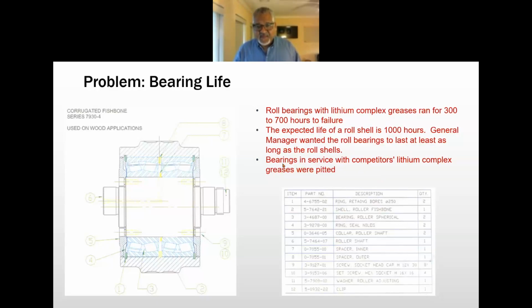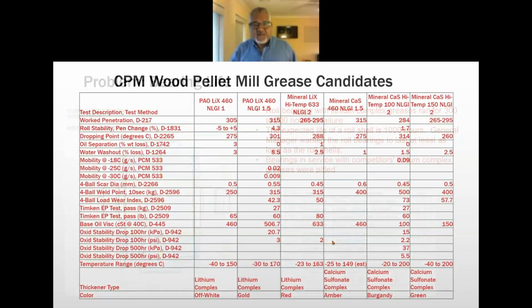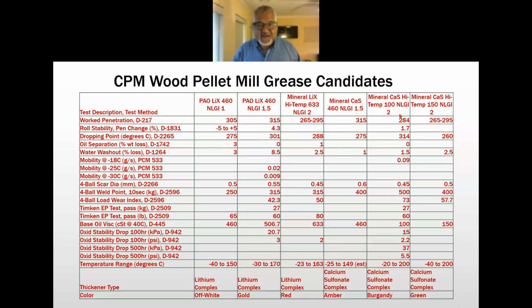The mechanics that were refurbishing the bearings were reporting that using a competitor's lithium complex grease, which exactly meets the specification of CPM, the bearings were pitted for sure. Okay, so we looked at different wood pellet mill grease candidates for a CPM wood pellet mill. We tried to stay close to their specs, but we also looked at calcium sulfonate greases that we would expect to perform well in the pellet mills.